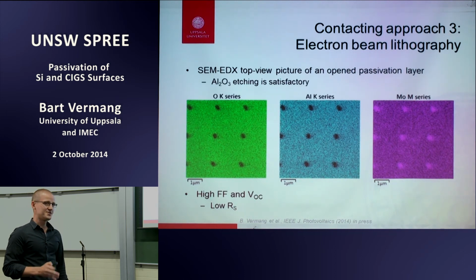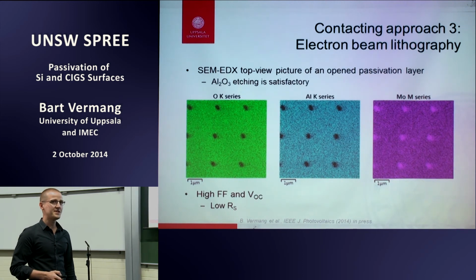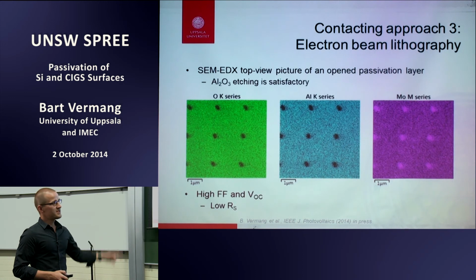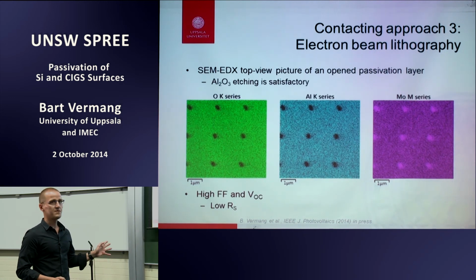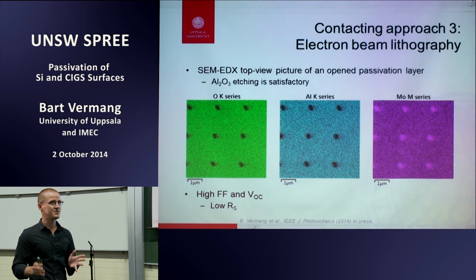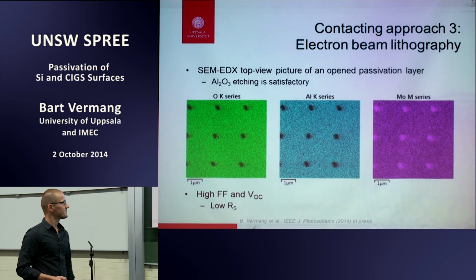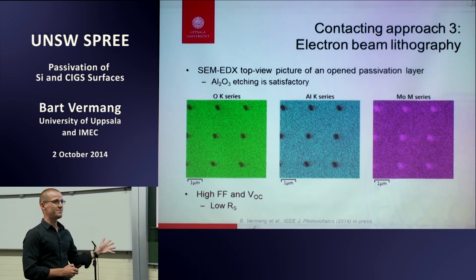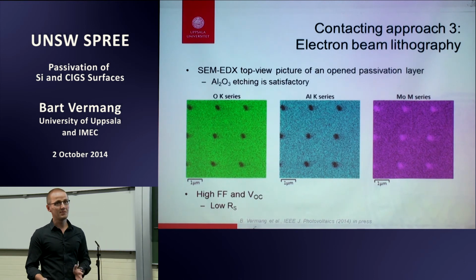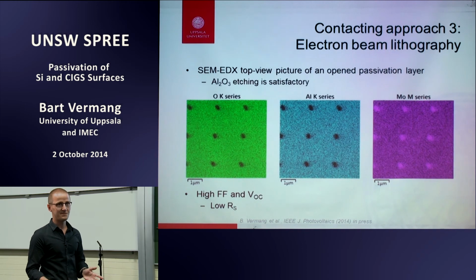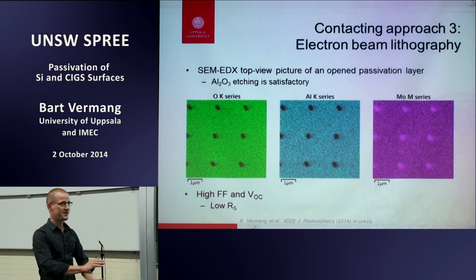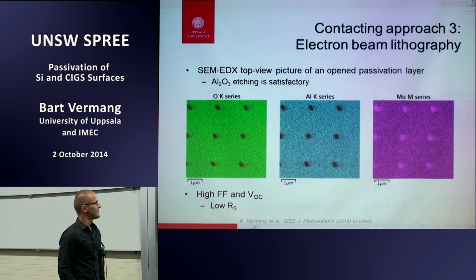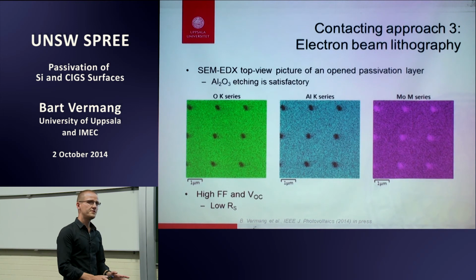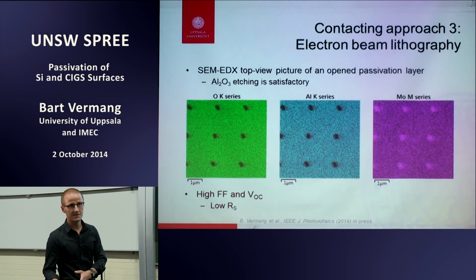Anyway, if you look in literature, getting 8 or 9% efficiency with those cells is very difficult. All our cells were really good, and we got efficiencies of 12-13% for a very, very thin layer, and really high fill factors. In literature, with very thin CIGS absorber layers, the first thing you see is that you lose a lot of fill factor. That's the reason I think this approach might be interesting for CZS as well. The big problem in CZS for the moment, at least to do research, is the fill factor. JSC and VOC are limited as well, VOC definitely. But you always have a quite low fill factor, which makes it difficult to do things and understand what's going on at device level.